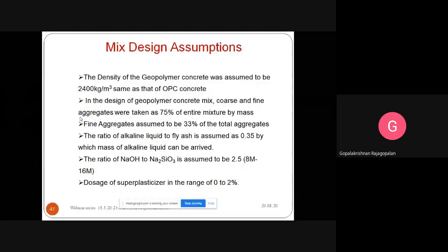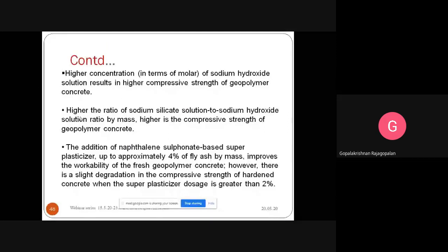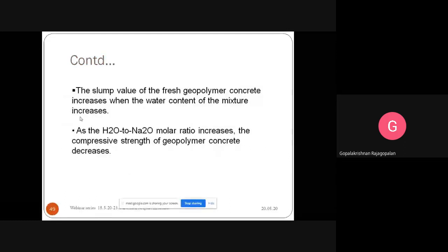From the experimental study, a higher concentration of sodium hydroxide results in higher compressive strength. A higher ratio of sodium silicate solution to sodium hydroxide solution by mass gives higher compressive strength. These are very, very important points. Till now, we have been hearing about what is meant by geopolymer concrete, what the chemistry is, everything. Now comes the mix design, very useful for your research work, for those faculty doing research and students interested in doing a UG project. If you want, we can use naphthalene based sulfonate superplasticizer up to 4%. Simply, we can keep it as required.